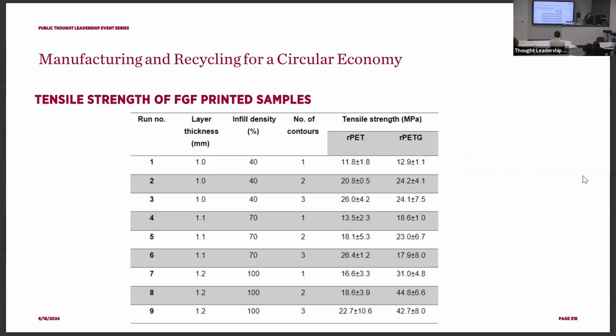And then we do the testing. We look at how strong they are, so that's the tensile testing. Basic tensile testing is just fixing one end and stretching the other end. We repeat the process, test all the samples, and find out the tensile strength. It's one of the main parameters for polymers. RPET is on the left-hand side, RPETG on the right-hand side. Conventionally, RPETG is stronger than PET, and in this case you can also see the results are a little bit higher than RPET. We repeat the whole thing, and we find that if we use 100% infill, RPETG shows very strong results, almost double the value of RPET.